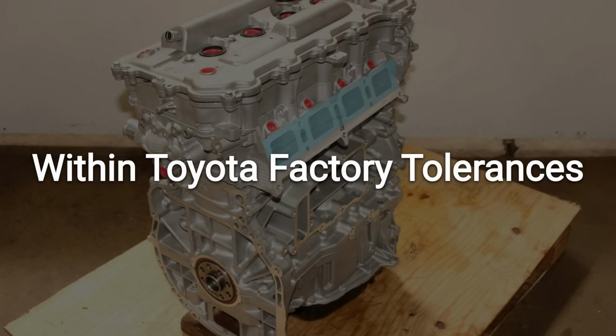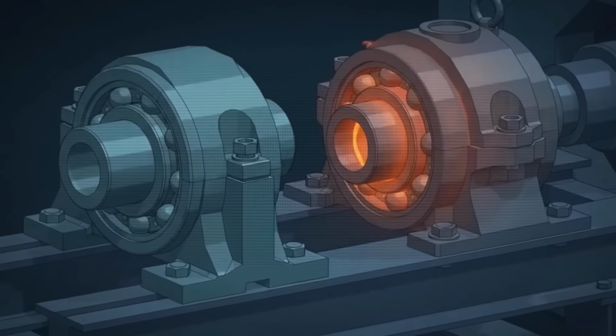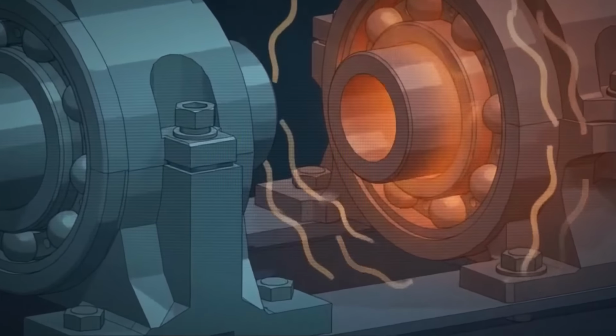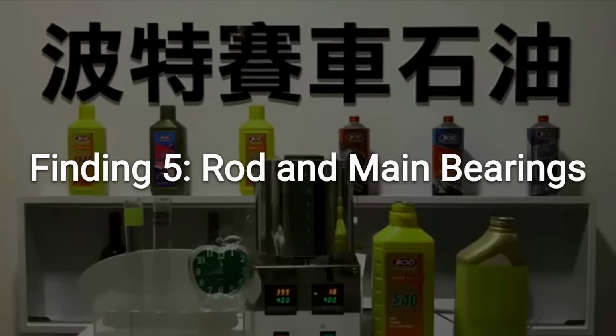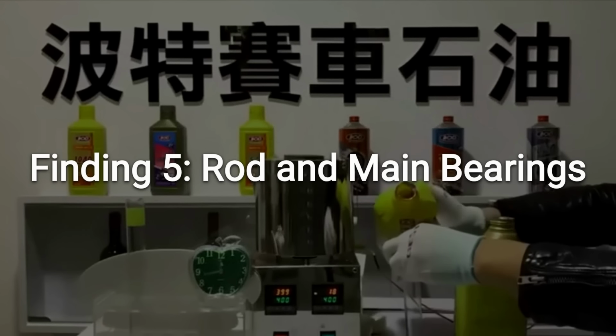Car A's bearings showed a very slight bluish tint on the number 2 rod bearing, which typically indicates minor heat cycling rather than actual damage. Car B's bearings looked essentially like new, with the copper bearing material fully intact and no visible wear pattern beyond normal break-in marks. This is genuinely the area where full synthetic oil showed its clearest advantage, because bearing protection depends heavily on oil film strength holding up under extreme pressure, and synthetic base oils are simply more consistent at maintaining that film across a wider temperature range than the factory fill blend.